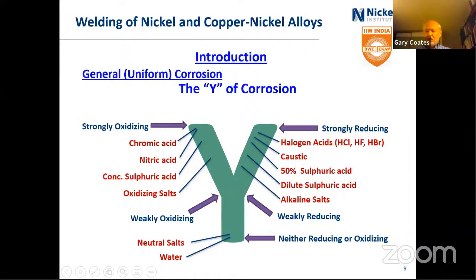So I have 2 slides on corrosion. The idea is that you really should understand where you use these chromium containing nickel alloys versus the non-chromium containing ones. So we talked about oxidizing and reducing before. Some of the chemicals that are oxidizing include things like chromic acid, nitric acid, concentrated sulfuric acid, oxidizing salts as we get weaker in the oxidizing nature. On strongly reducing, we have the halogen acids, hydrochloric, hydrofluoric, hydrobromic are strongly reducing, caustic, sodium hydroxide, potassium hydroxide, 50% sulfuric acid. And as we get to dilute sulfuric, it's getting weaker on the reducing area, but still reducing there.